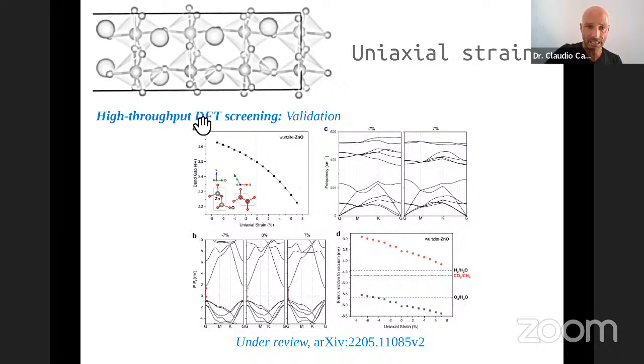On the other hand, this increase of the band gap here is more related to the value of the crystal field. So here there is no significant band splitting or band degeneracy lifting effect, so this increase is not due to symmetry breaking. It has more to do with electrostatic effects. Anyway, we already kind of knew this. We checked that the vibrational properties were fully maintained.